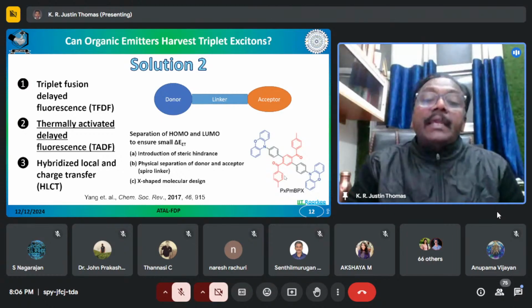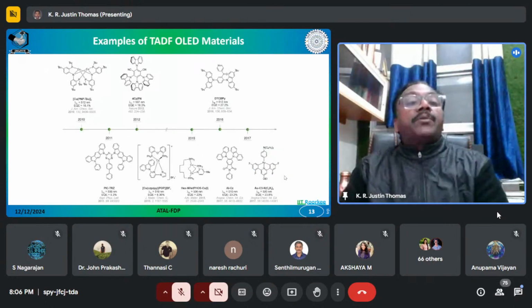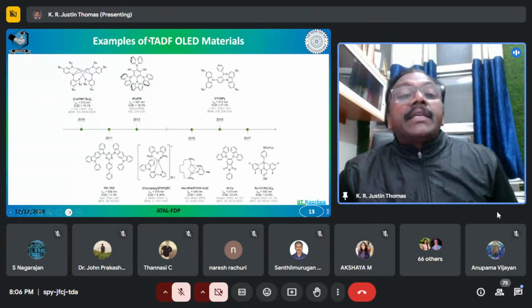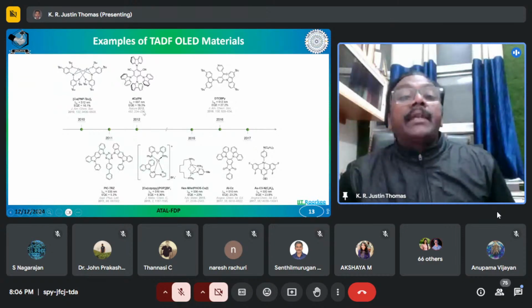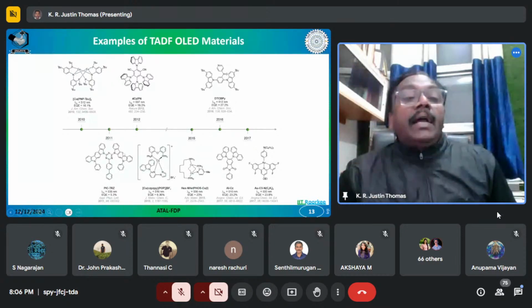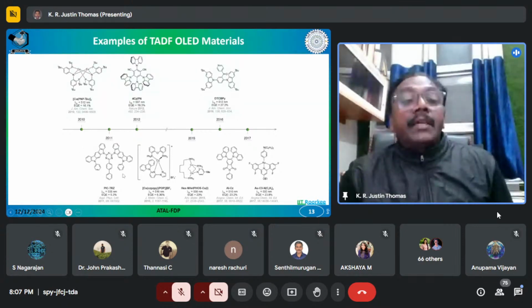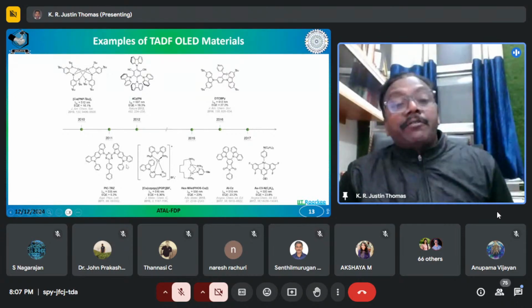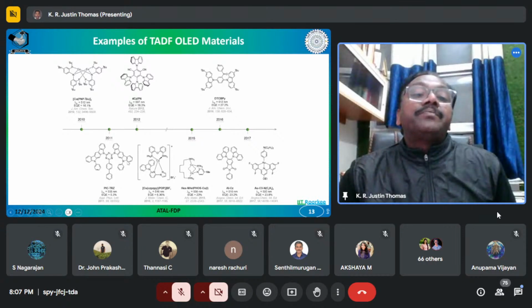Now let's look at examples of molecules that are reported in the literature. You can see that this is the sterically crowded molecule 4CzIPN showing an efficiency of 19.3. And this molecule was reported in 2011, where you have a donor-acceptor structure and, because of steric hindrance, one can say sterically crowding is there. That leads to a tilting and then effective separation of the HOMO and LUMO.